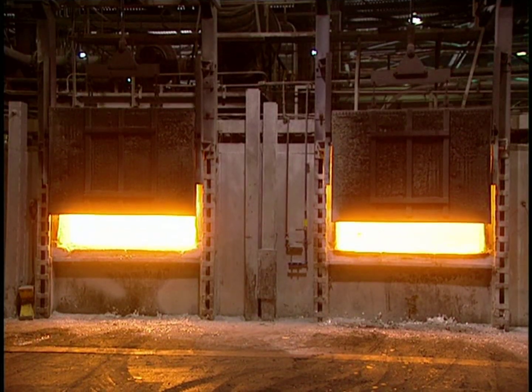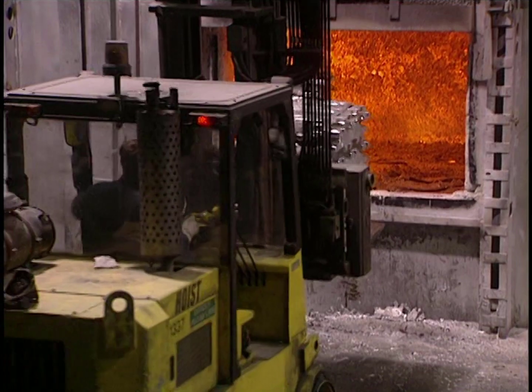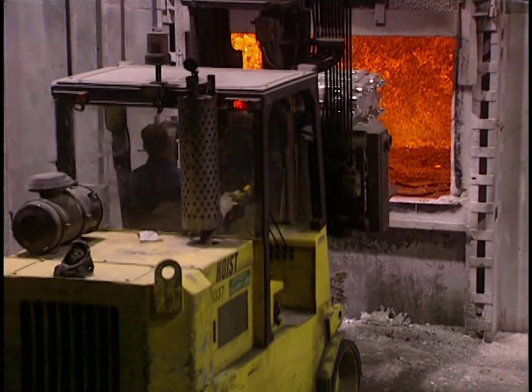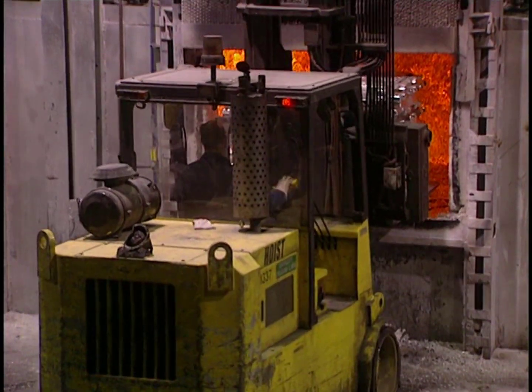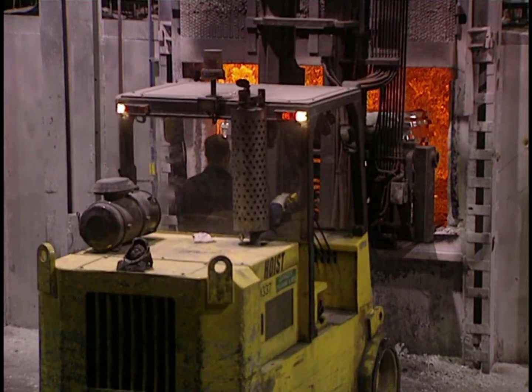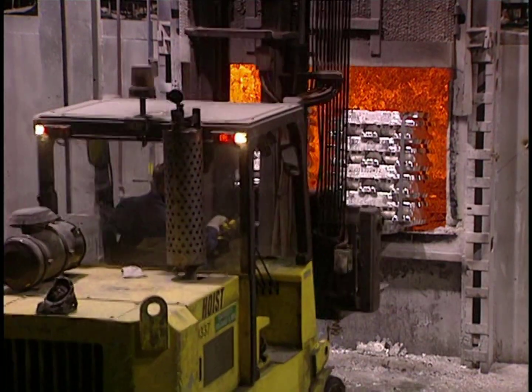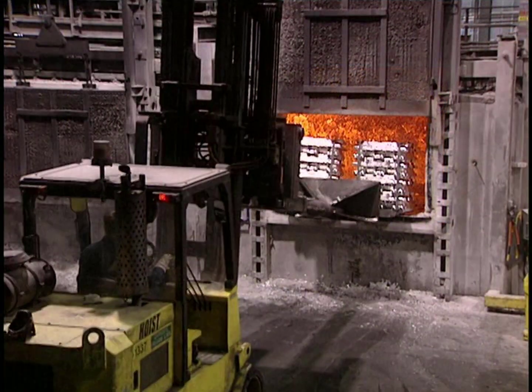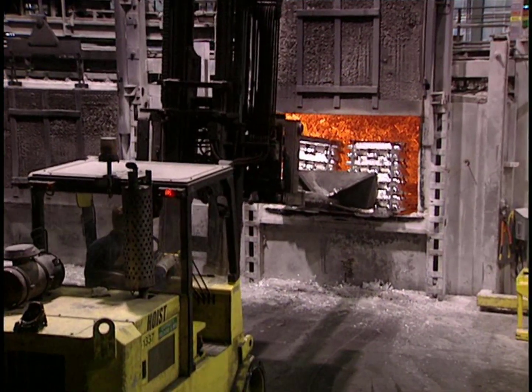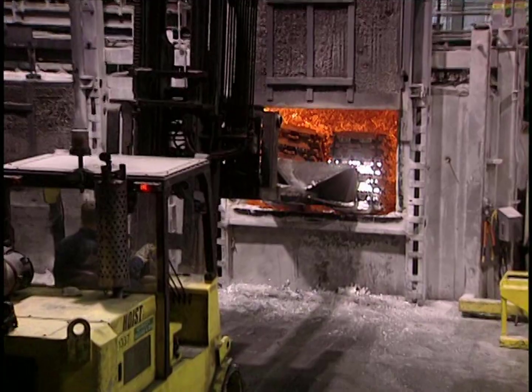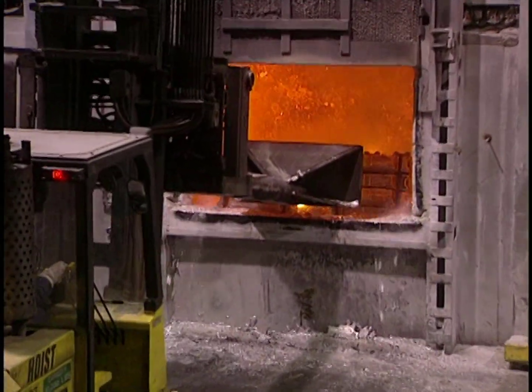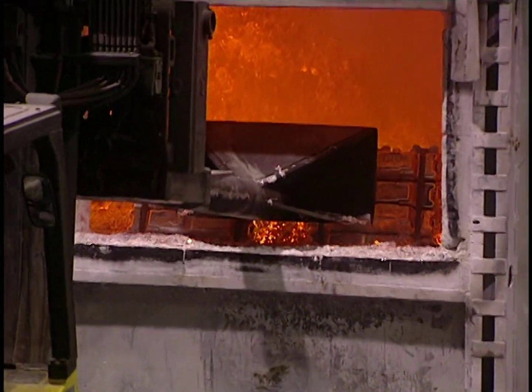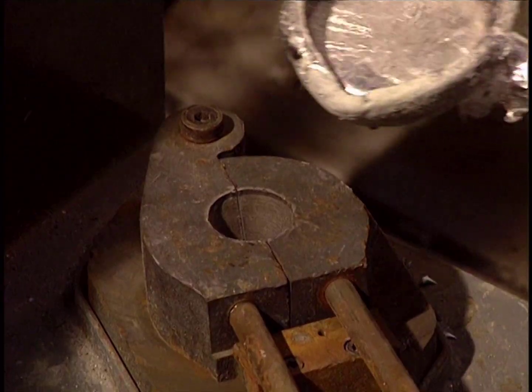We begin by melting ingots of 100% pure aluminum in a natural gas furnace. These ingots, called pigs, are essential in alloys with zinc, titanium, and silicon. It takes 3 to 8 hours to melt 30 tons of aluminum in this remelting furnace, which operates at 1,380 degrees Fahrenheit. The fusion temperature of aluminum is 1,220 degrees Fahrenheit.